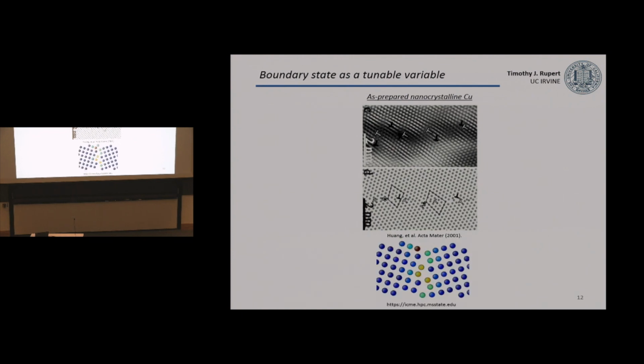From a modeling perspective, you can also think about this as I put 2 crystals together. I can cut my crystal, take it, I can tilt it in different directions, and slap it together. But that's not necessarily the lowest energy configuration. If I want to find the lowest energy configuration, I'd have to shift it around in certain directions and maybe even think about adding and taking out atoms to find the lowest energy state. Okay? So this extra disorder happens when I just slap it together. I can relax it and find a lower energy state.